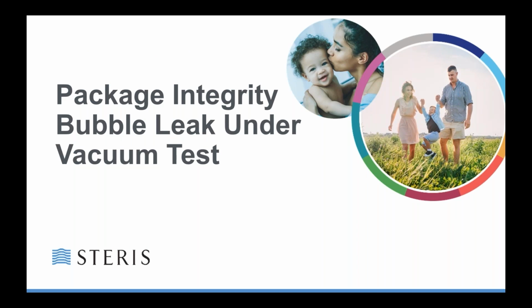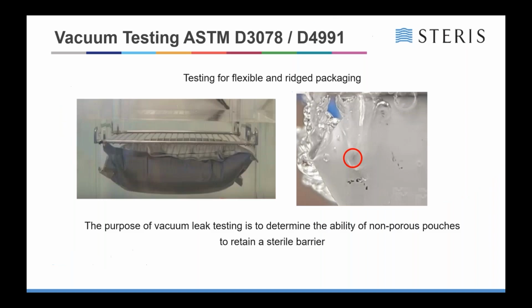Bubble leak test under vacuum is another very good test, again a whole package integrity test, and it can test foil and foil type packaging or non-breathable packaging. It's very easy to do, because all you're doing is submerging the product under water, applying a vacuum to the test, and looking for a continuous stream of bubbles from the pouch. Again, it's for non-porous pouches. It doesn't work with porous type pouches.